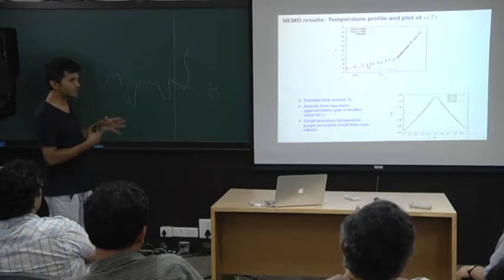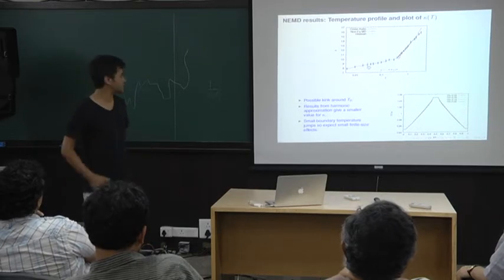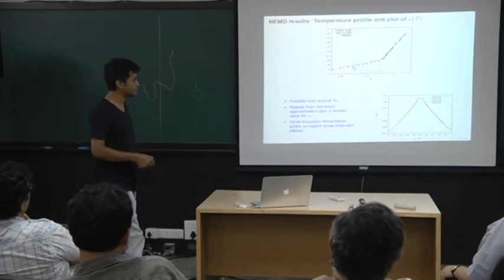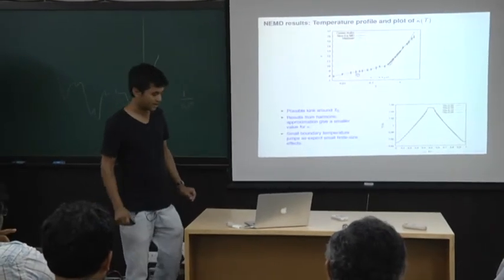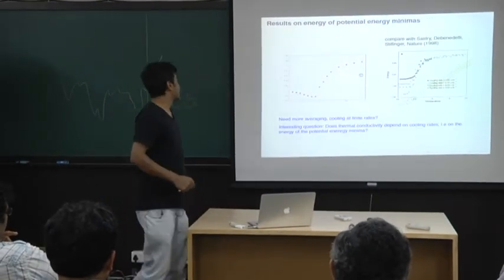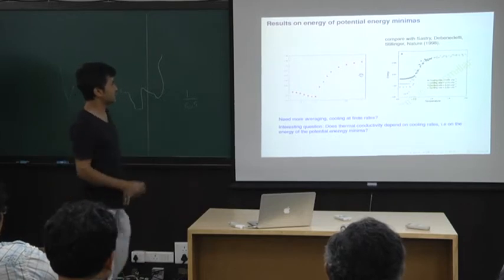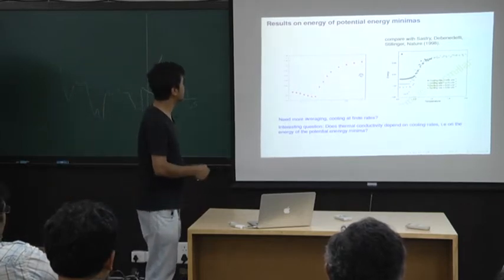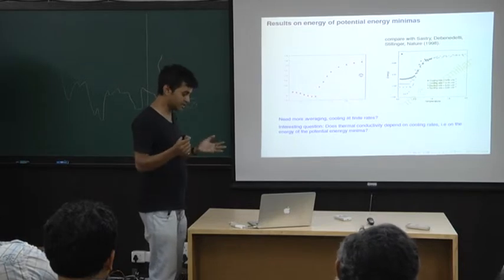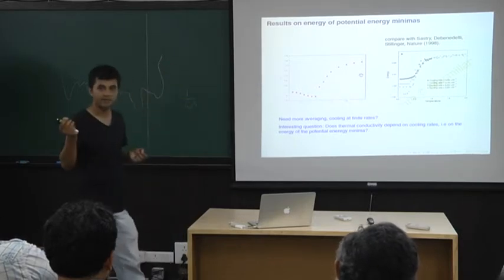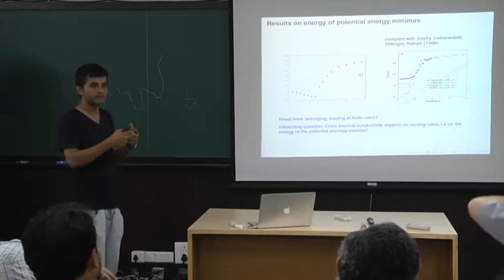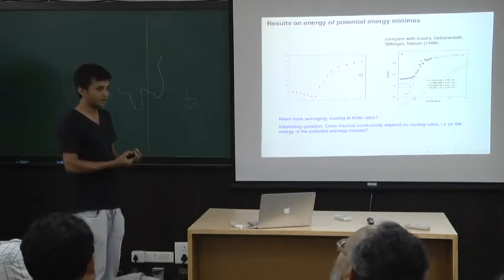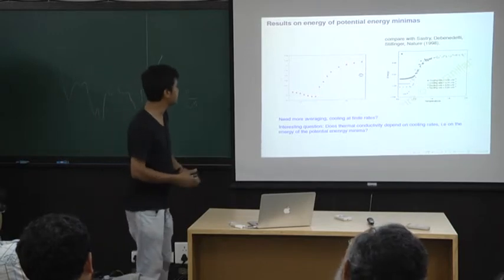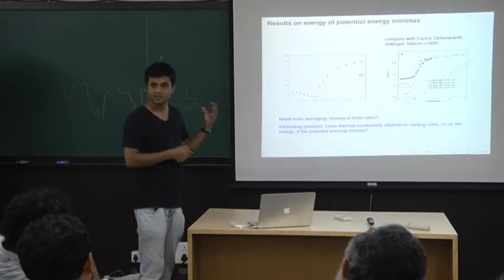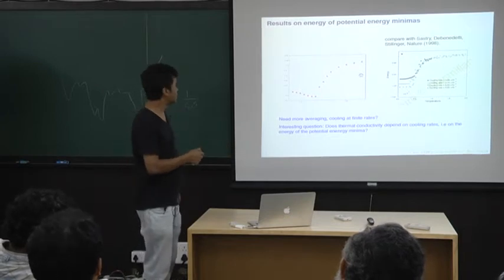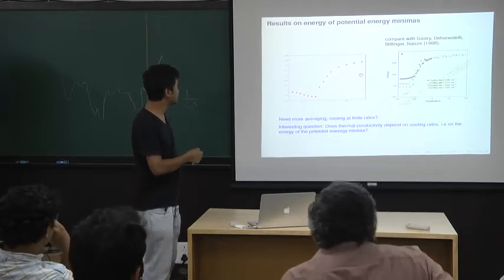One thing one always has to worry about in these systems is finite size effects, and we believe that they are small because you don't see temperature jumps at the end. This is something Shrikant just mentioned. Right now what we are doing is a very fast quench. We take the system from a high temperature, bring it down to low temperature, equilibrate for some time, and try to find the minimum energy configuration. If you ask what is the minimum energy that you reach as a function of temperature, it looks something like this.